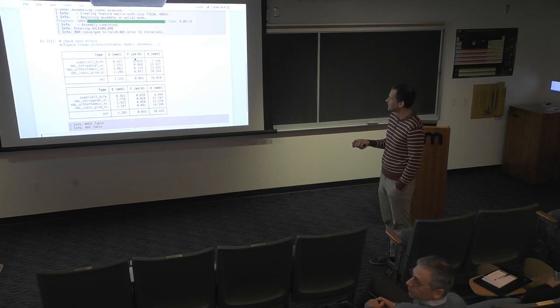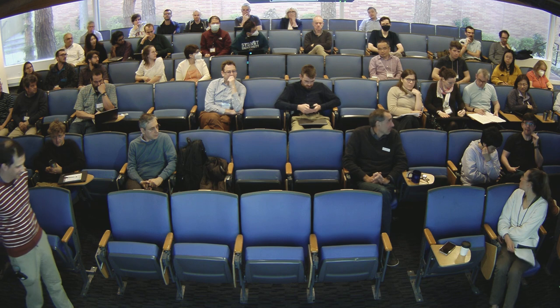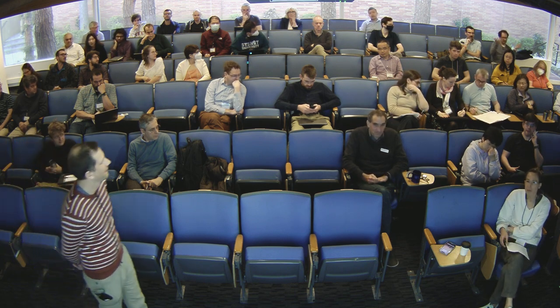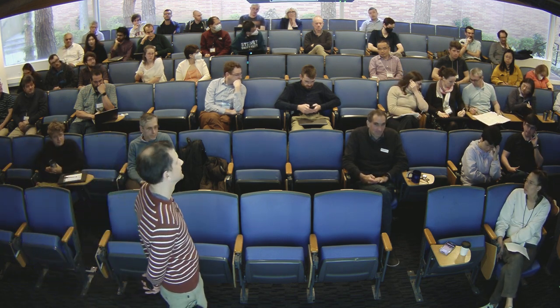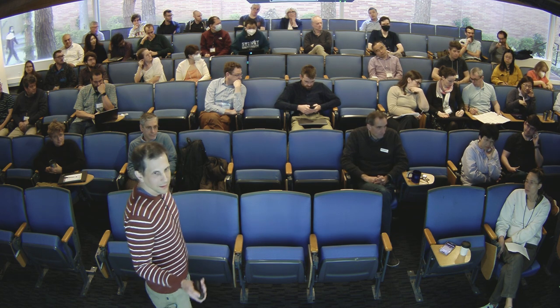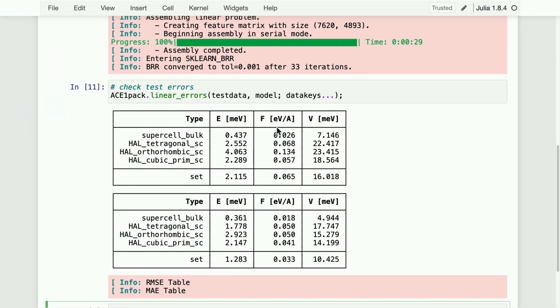I mean, the whole uncertainty quantification business, so what accuracy on energies and forces do you need for some macroscopic property that changes? It's a whole super interesting thing that nobody knows, and one can just get into it. But here you're seeing about two milli-eV per atom. For a material model where not multiple crystal phases are present, you could get 1 milli-eV, sub-milli-eV. This will give you decent phonons and phase diagram. This perovskite phase diagram is fine.